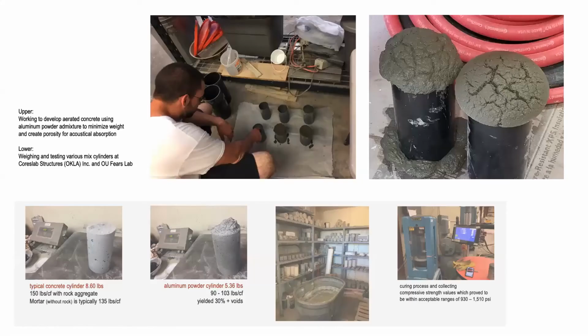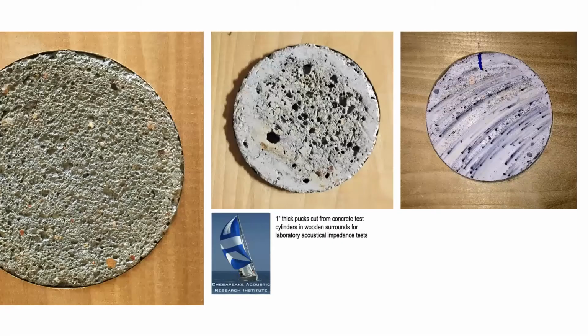Literature reviews and experimentation led the team to begin exploring concrete for its potential as an acoustical material. The recipe and shape can complement density to provide reflection, diffusion, and absorption of sound waves. Concrete samples containing variations of numerous additives such as flax, silicon oil, nacre, crumb rubber, vegetable fibers, pumice powder, walnut shells, and aluminum powder were developed and tested.